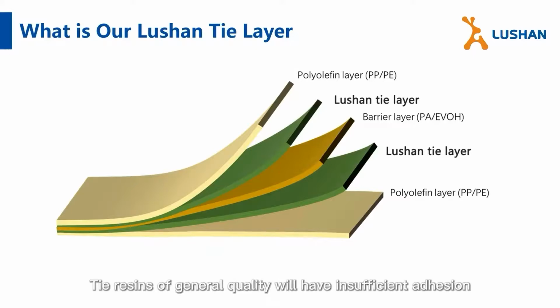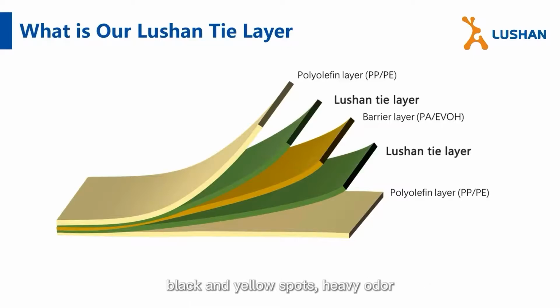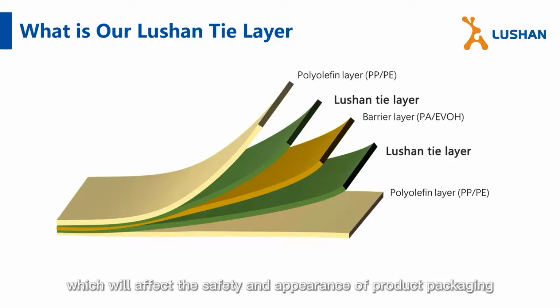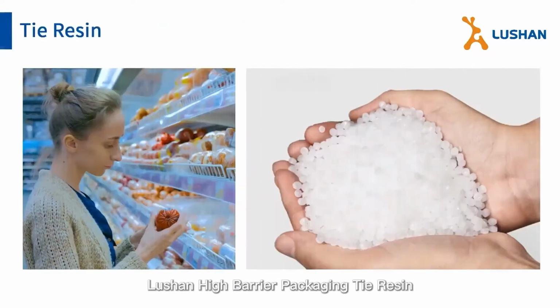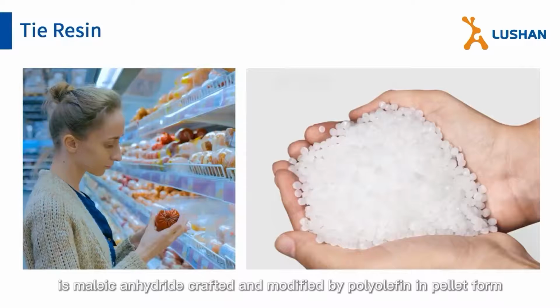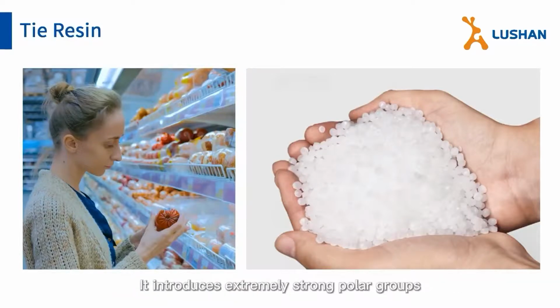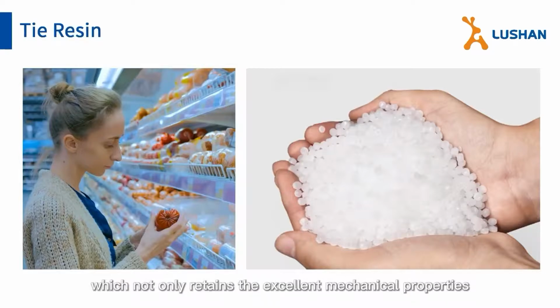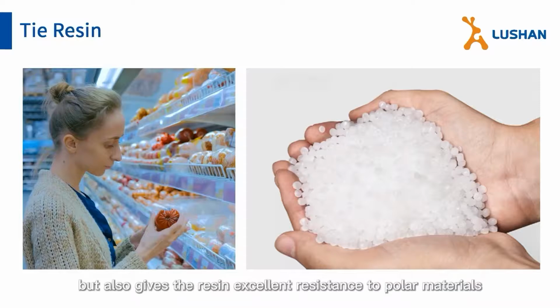Tie resins of general quality will have insufficient adhesion, resulting in peeling off, uneven particle color, black and yellow spots, heavy odor, poor processability, and obvious crystal spots, which will affect the safety and appearance of product packaging. LUSHAN High Barrier Packaging Tie resin is crafted from polyolefin modified by maleic anhydride, in pellet form. It introduces extremely strong polar groups into the molecular chain of polyolefin resin, which not only retains the excellent mechanical properties of polyolefin materials, but also gives the resin excellent resistance to polar materials.